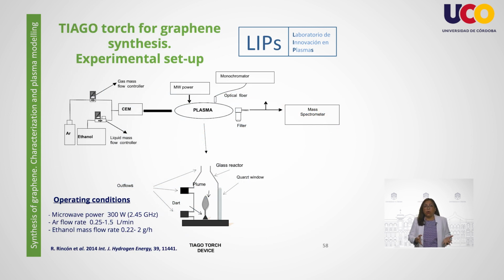Let's now take a look at the whole experimental setup at the Laboratory of Innovation in Plasmas. This is composed of the Tiago torch itself, connected to a microwave power generator, to a gas flow system, and to the characterization tools, which are: one, the optical emission spectrometer, composed of a monochromator and an optical fiber that collects the radiation emitted by the plasma just above the tip of the torch, and the mass spectrometer, which is connected to a lateral outlet of the reactor for the monitoring of the exhausting gases.